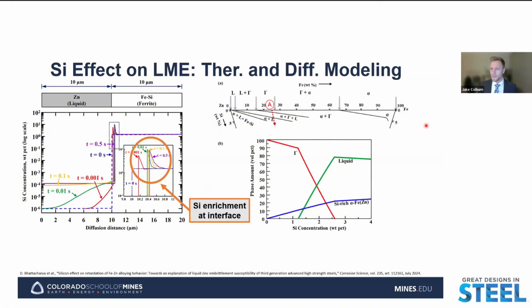And so that's where, if we look here at the zinc and iron-rich corners of the zinc, iron, silicon ternary phase diagram, we can pick a composition ratio of iron and zinc that we see at the interface, and then begin to add silicon while maintaining that iron to zinc ratio at the interface. And so from that, we can then calculate what the fraction of phases that we expect to be formed there. So this is the equilibrium volume fraction of each of these phases at 700 degrees C for increasing silicon concentration. So here we're adding silicon to the local composition at the interface.